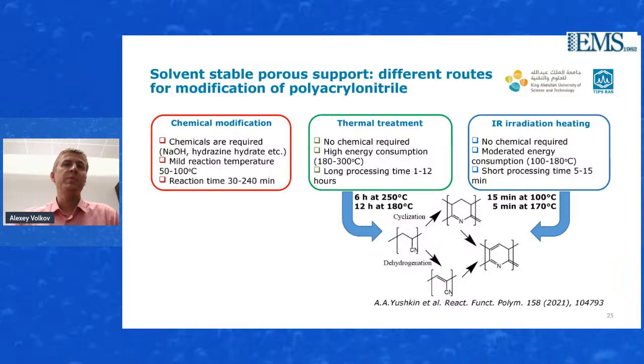And today we will focus more on the third option, that's infrared irradiation heating, because in that case we don't need to use extra chemicals, and also we can significantly reduce the processing time from 1 up to 12 hours down to 5 or 15 minutes. Because if we think about the upscaling, we have to keep in mind also how that approach could be applied on the industrial level, and a thermal treatment which might require several hours might not be durable for the large scale.